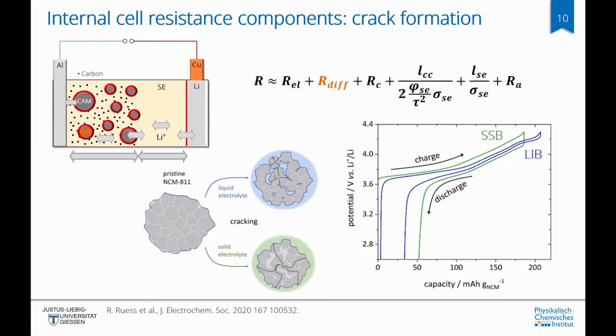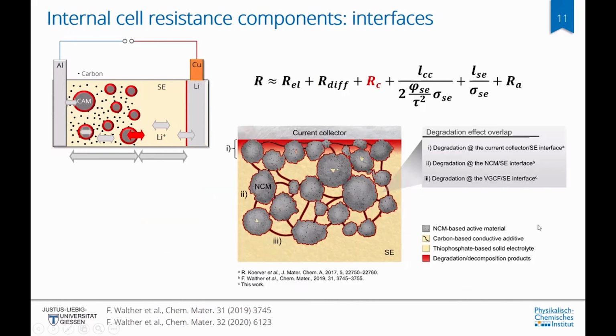With liquid electrolyte, the liquid can infiltrate the cracks, thereby maintaining contact throughout the particle and having short diffusion pathways. However, the solid electrolyte cannot infiltrate the cracks, which is why we have obtained significant cell performance loss because of the cracking and longer diffusion pathways lithium has to transport inside the cathode particle. This means that we see cathode active material development for solid-state batteries to be one of the key aspects.